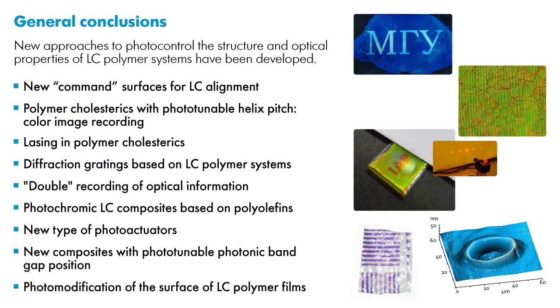Let me summarize our results. In our work, new approaches to photocontrol of the structure and optical properties of liquid crystalline polymer systems have been developed. In particular, we have obtained new command surfaces for liquid crystalline alignment, polymer cholesterics with phototunable helix pitch and realized color image recording, lasing in polymer cholesterics, diffraction gratings based on liquid crystalline polymer systems, double recording of optical information, photochromic liquid crystalline composites based on polyolefins, new type of photoactuators, new composites with phototunable photonic bandgap position, and recently we demonstrated new possibilities of photomodification of the surface of liquid crystalline polymer films.